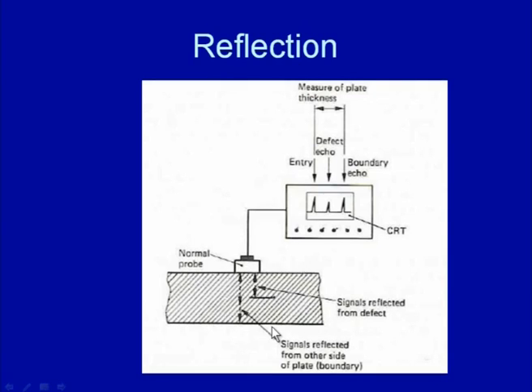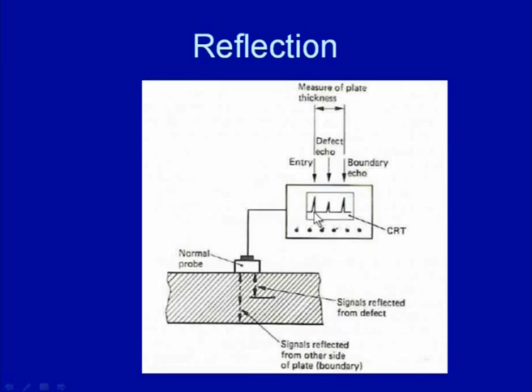So, the first peak and last peak are the peaks coming from the top surface and the bottom surface, but the moment we get an intermediate peak, that will indicate that some internal discontinuity is present, and the location of this intermediate peak will indicate the location of the defect between the top surface and the bottom surface. If this corresponds to the top surface peak and this to the bottom surface peak, the relative distance between them can be calibrated to see exactly where the defect is present. So, this is how the ultrasonic test is conducted.